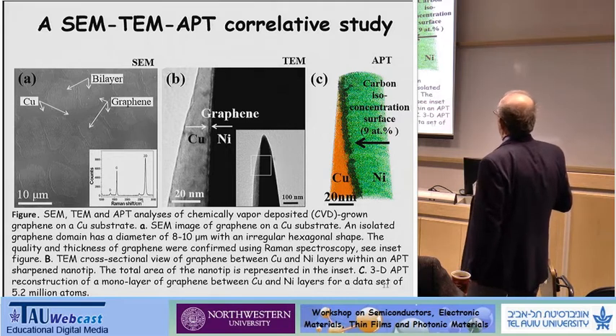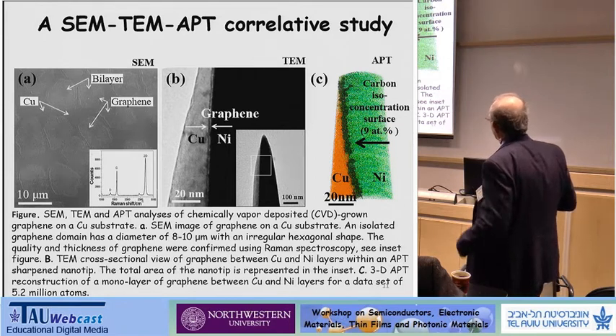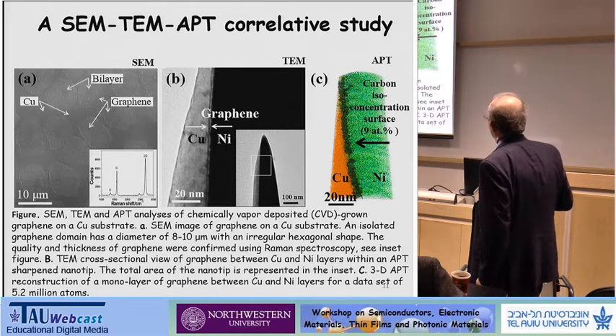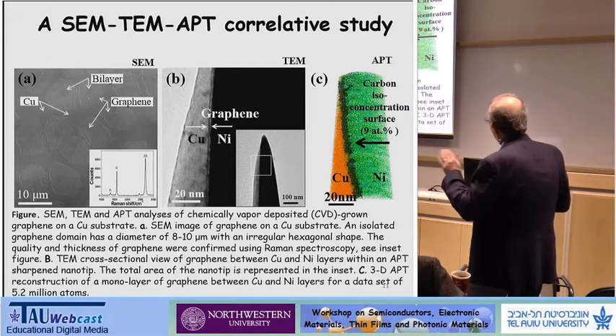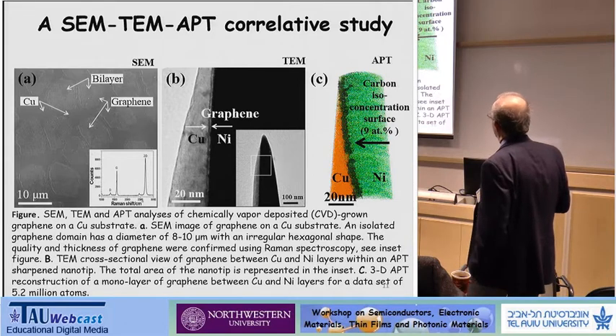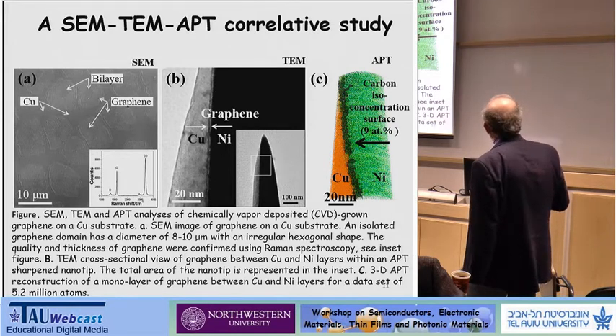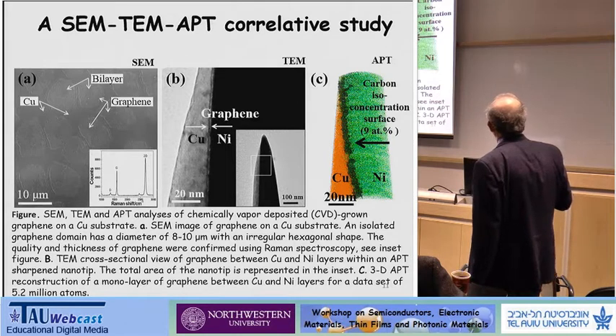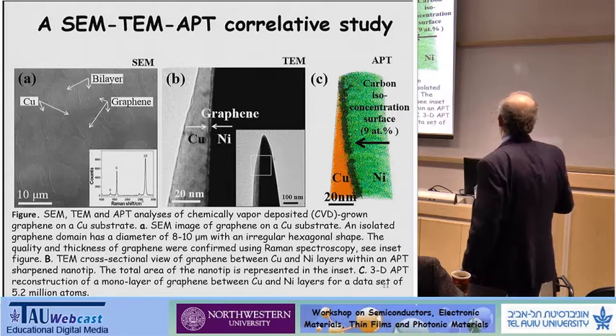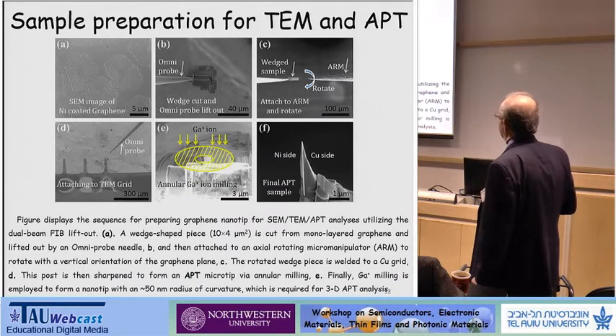Okay, now this is a TEM micrograph of this tip, and I'll explain in a second how we prepared the specimens. This is the copper foil on the left-hand side. Here is the graphene layer, and then here is the nickel, which is deposited on top. So you have a sandwich consisting of copper, graphene, and nickel. And over here is the graphene, and we use a carbon isoconcentration surface of about 9 atomic percent to define the graphene. So you see all 3, and it's broadened, and I'll talk about that a little bit also.